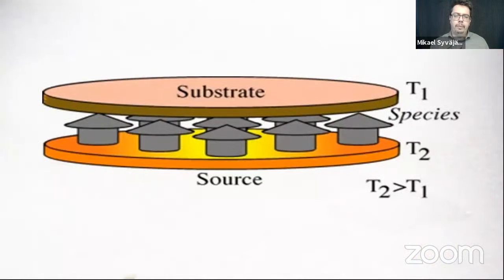And what we did at that time also was to take this method where we have a source and a growing seed, and then instead of having a long distance to grow bulk material to make wafers, we decreased this distance. So we had a source of solid ceramic silicon carbide instead of powder. And then we decreased the temperature and we could have a similar type of PVT method, but for growing thick films. At that time, the motivation was that you need thick films for the power devices, and the power devices were the main motivation for developing silicon carbide, and silicon carbide has the properties for that.